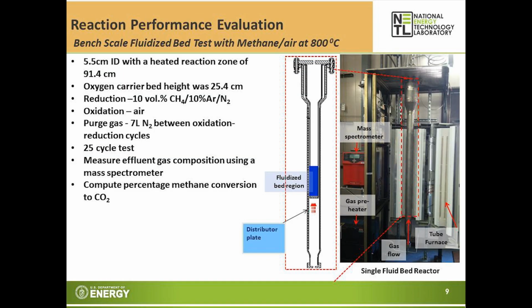Okay, the initial reaction performance evaluation was done in our bench scale fluidized bed reactor. We use about 25.4 centimeter bed height, and we introduce methane for reduction and then air for oxidation, and we conducted a 25 cycle test, and we measured the effluent gas stream using a mass spectrometer. And then using the data, we computed the percentage of methane conversion to CO2.